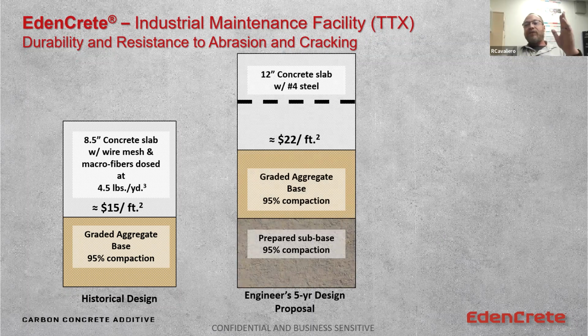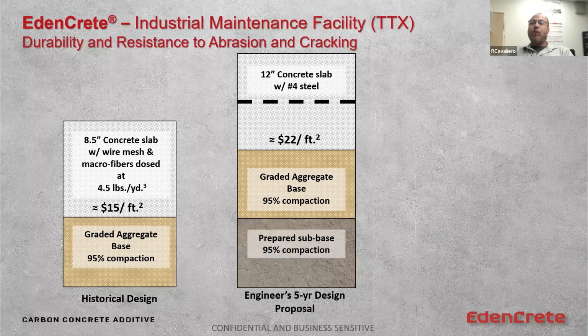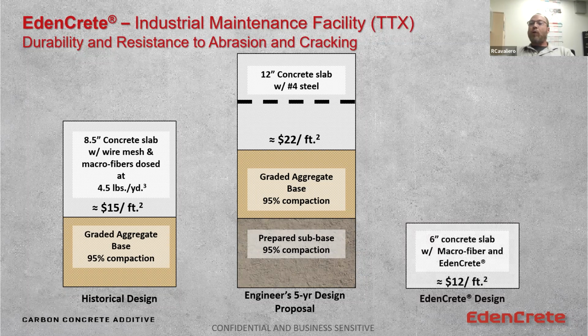You just need to excavate 24 inches and give me 6 inches of coarse soil compacted, 6 inches of GAB compacted, and a 12-inch thick slab with number 4 steel. It'll only cost you $22 per square foot. And he says, "Well, what did you do with EdenCrete?" He says, "Well, I ripped out about 6 inches. In some areas it's 4, some areas it's 7. I basically used macro fiber with no welded wire mesh, and I poured it back."